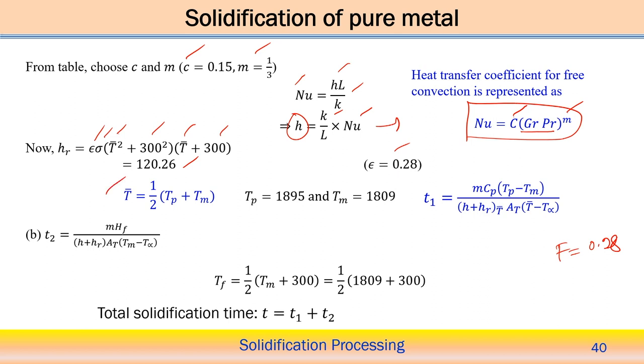Now the average T bar is also calculated, TP is 1895 and TM is 1809, all these values are already calculated. So from there we can estimate the solidification time to go from the peak temperature TP to the TM temperature. So here, MCp, TP minus TM, over H plus HR at the values of the average temperature T bar, and then here A, the cross section area, times T bar minus T infinity.